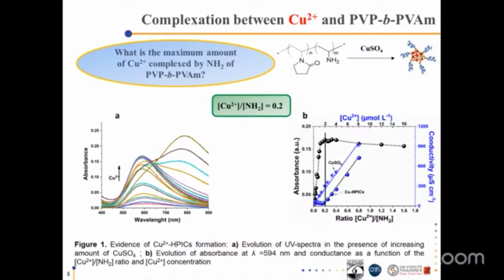Hence, absorbance and conductivity measurements highlighted the formation of the complex, with complete complexation when the ratio between copper and amine groups of polyvinylamine blocks is close to 0.2. It should be noted that the same result was previously described in the literature for the complexes between polyvinylamine homopolymer and copper. Next picture, please.